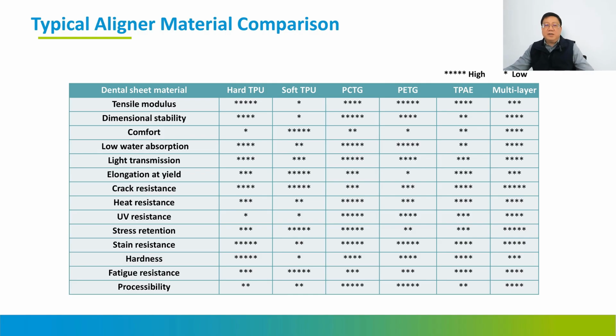So in general, I summarize the above-mentioned properties. These are all the requirements for a good aligner, what kind of properties they need. Starting from tensile modulus, dimensional stability, comfort, low water absorption, light transmission, low elongation yield, good crack resistance, heat resistance, UV resistance, stress retention, higher stress retention, and good stress resistance, with moderate hardness, fatigue resistance, and very good processability. In general, you can see the right side is the best combination, which is a multi-layer.